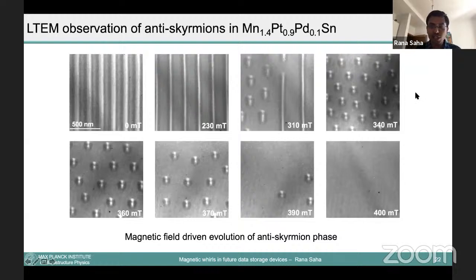So you can see this is the real image of anti-skyrmions, obtained from the microscope. These are the one-dimensional helical structures. When you apply a magnetic field, they form something like that. So each one of them will be a potential element for data storage in future, and each one of them will store 1 bit. Their presence will be 1 bit, their absence 0 bit. So if you can increase the density, for example, in this space, instead of 20, if it is 2000, you can imagine the data density in the same space increases by at least 2 orders of magnitude.